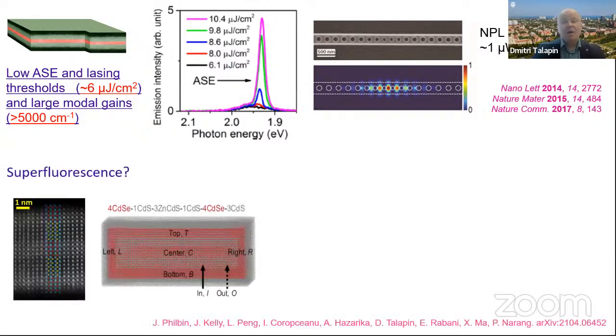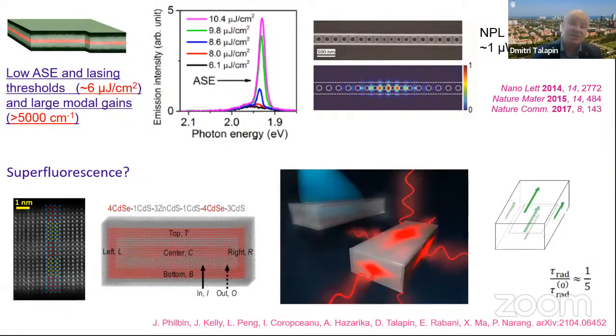commercial market. Now, we are going after even more complex phenomena, such as, if you have multiple stacks of multiple quantum wells, you can generate new quantum states of matter. You can couple excitations in different quantum wells to the same optical field, and we see some early spectroscopic signatures of superfluorescent response, where the individual quantum wells in our epitaxial stacks synthesized in solution can couple together and act as a single quantum system, preserving phase coherence between, involving multiple chromophores, multiple quantum wells. And it's just a first step of the exploration, because whenever you have a platform for material design, it typically leads to interesting developments.